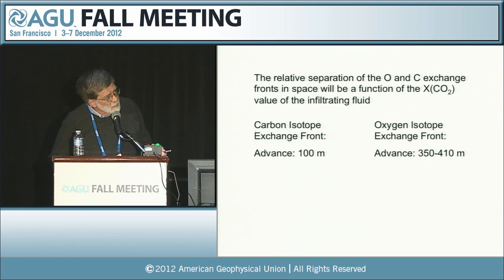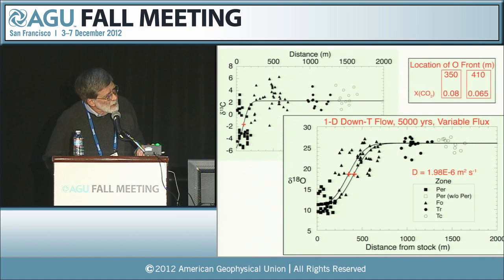Okay, so the separation of the oxygen and the carbon fronts is a function of the mole fraction of CO2 in the infiltrating fluid. So we looked at that. What I've shown here in the bigger front profile is the oxygen isotope profile with distance, with a couple of the solutions for the different fluxes that match the two center points that I've estimated of 350 and 410. And in the back is the carbon profile.